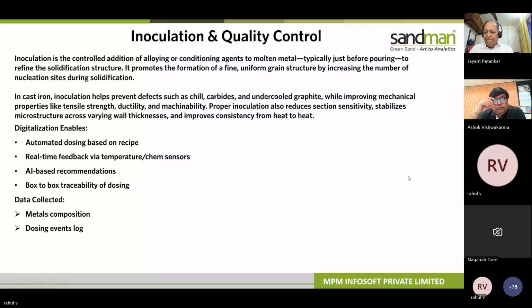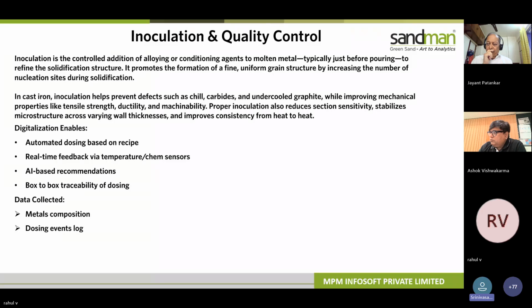Okay, but what my question is, slag deposit does not directly reduce it by 100 kg; it will slowly deposit in the furnace lining. Yes, sir. As I told earlier, we need the help of digitalization over here, sir. We need to have a track of what's happened in the furnace. Even slag deposition should be monitored. We have to have the furnace event logs as well as the weighing scales of the furnace, so that the weight in the furnace can be tracked in real time.